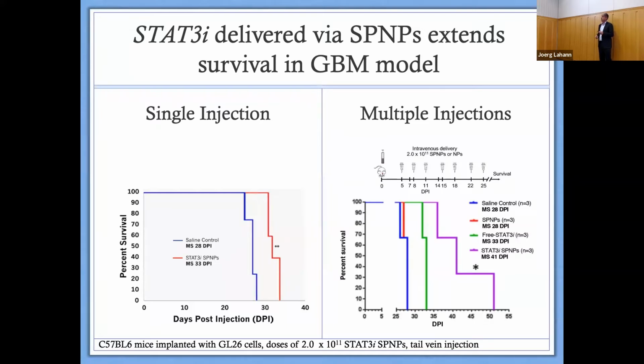Then what we did is we followed that up with multiple injections. So it's a cascade of these injections over 25 days, or 20 days, actually. And now we see even higher benefit from the nanoparticles, much better than the free STAT3 inhibitor, where we see pretty much nothing, or a little bit. And obviously with the control or the particles themselves, the mice die very, very rapidly. Now, STAT3 is a hub, but even in vitro, when we do our IC50 measurements, it's relatively non-lethal, right? So it's not a very lethal pathway, but combining it with a second method seemed to be very interesting.